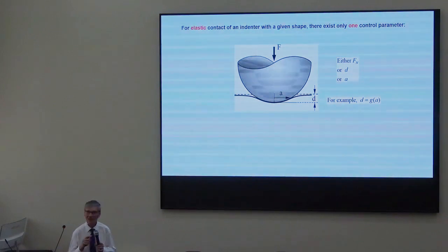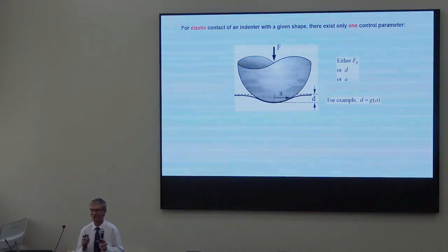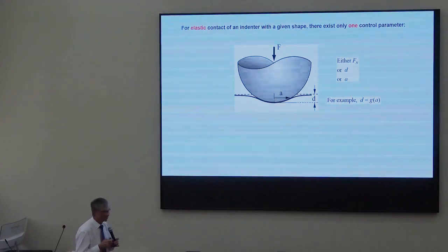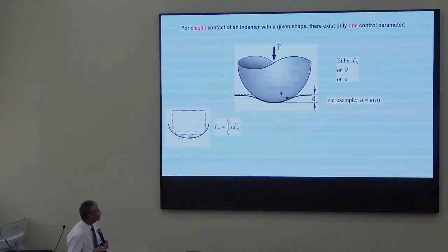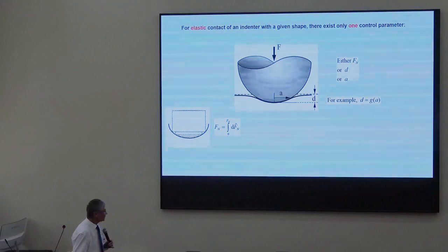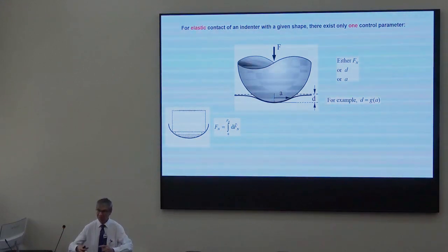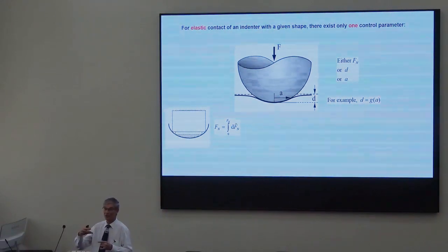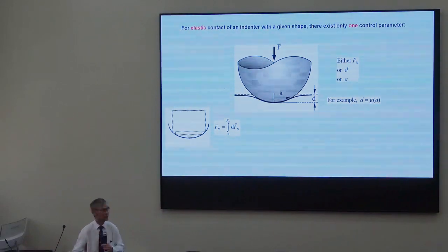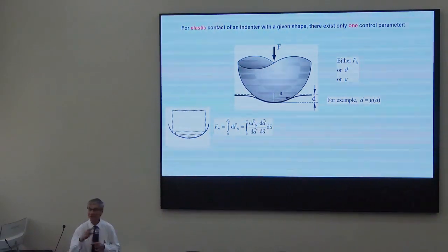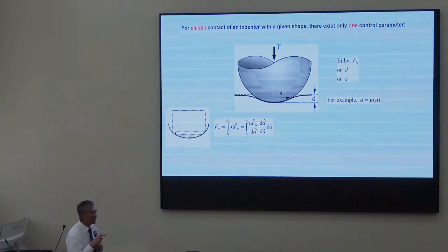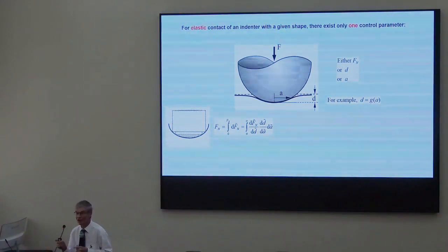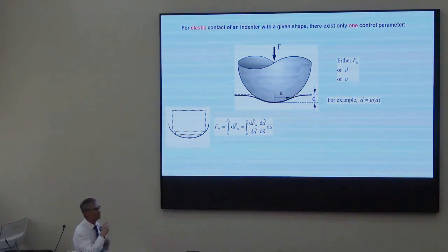This relation does not depend on the elastic modulus. This is the most universal relation of all of them. And now we consider indentation, and it is a sum of micro indentations, and the force at the end of the indentation process is the sum of incremental forces, the integral of dF, but the force is a function of indentation depth, and indentation depth is a function of the contact radius. And so we can just go over to the integration over contact radius.